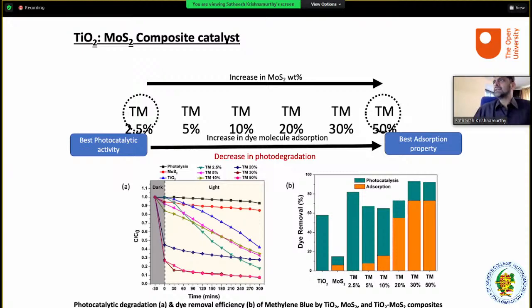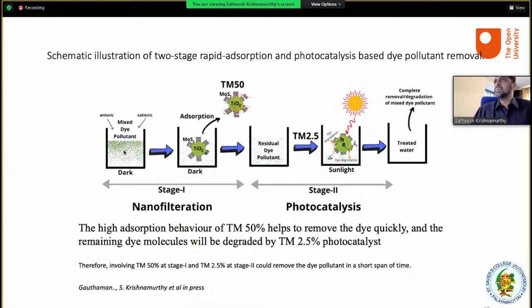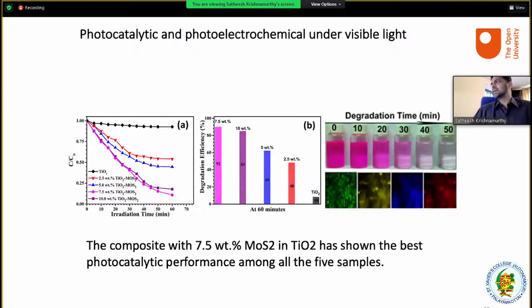Okay, in the process, we mix the pollutants, not only one pollutant, we mix all the pollutants. How does this happen? I mean, two stage. So 50% acts as an absorber, it takes up the residual dye, then we put in the 2.5% for photo degradation, and we treat the water. Okay, and that is how it is.